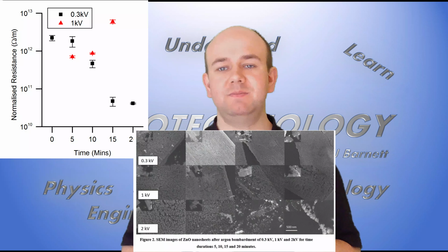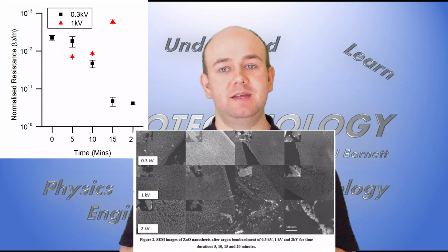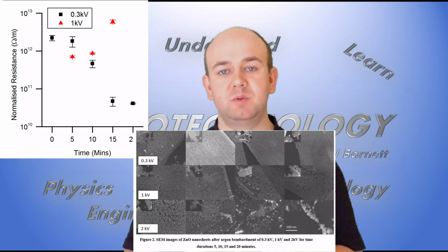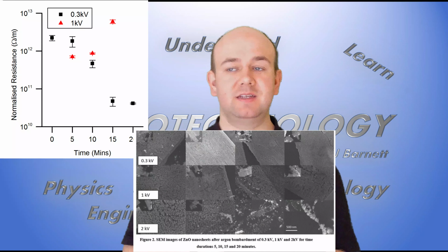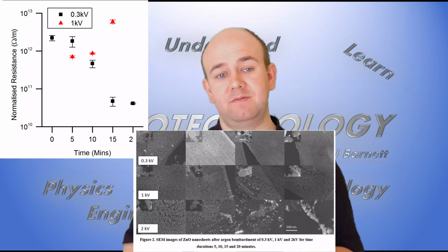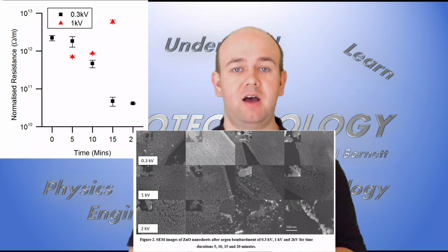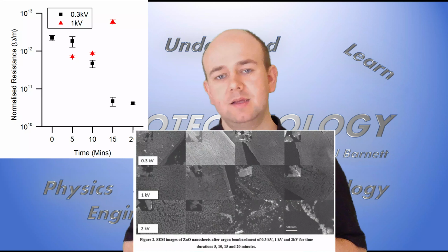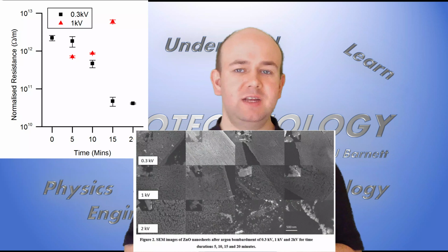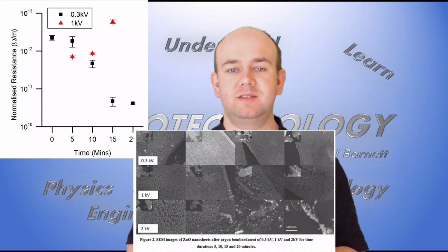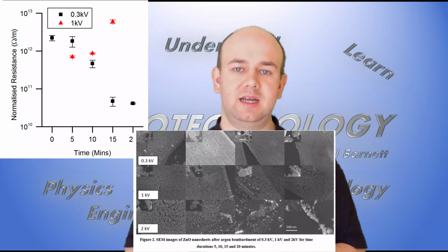The 2 kV seemed to be just too powerful to do the experiment fully with, so even for a small amount of time you were getting significant damage to the sheets, and for long periods of time, we ended up with hardly any sample at all. So if you read through this paper, and there'll be links down in the description below, you'll see that we've got an incomplete data set for the 2 kV measurements.